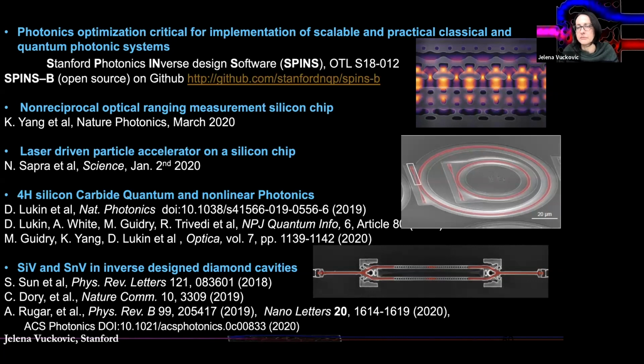And the second question here is, is it compatible with data rates above 10 gigahertz? Yes, so we did demonstrate 10 gigahertz operation. The high-speed measurements that are also in our paper are at 10 gigahertz. We showed that we have transmission forward, backward blocking at 10 gigahertz. We only had the equipment for 10 gigahertz operation, but it should actually work at higher speeds, also 30 gigahertz. But we didn't really have a pulse generator for 30 gigahertz to perform experiments.